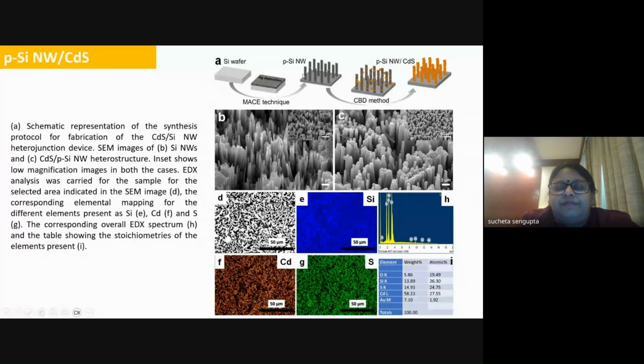On that, with H2O2, we chemically etched the surface of the silicon wafer to produce uniform silicon nanowires. And on that, we followed chemical bath deposition with the help of a cadmium precursor and a sulfur precursor, and these silicon nanowires are uniformly coated with cadmium sulfide nanoparticles.